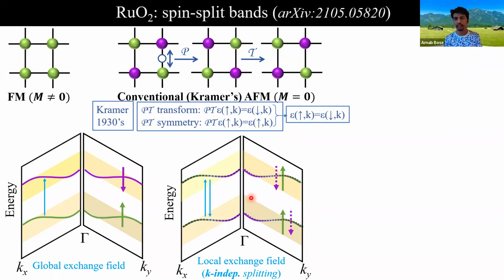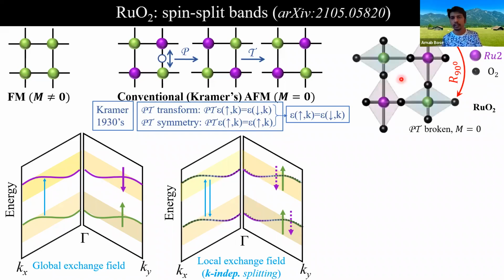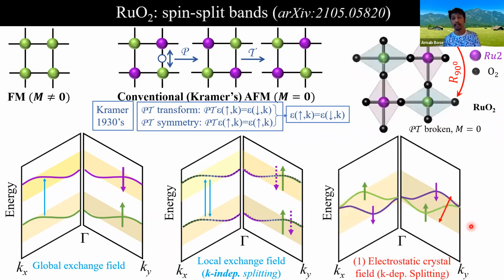Now let's have a look at what happens for the single crystal ruthenium dioxide that we are interested in. So this is the crystal structure of ruthenium dioxide. These are the non-magnetic oxygen atoms, and these are ruthenium atoms. So 2 sublattices, one is up spin, another is down spin, resulting in net magnetization of 0. Now, if we ignore these non-magnetic oxygen atoms, then it exactly looks like this standard collinear antiferromagnet. But the moment we consider the non-magnetic oxygen atoms, it immediately breaks PT symmetry. Rather, we have 90-degree rotational symmetry. So in this case, we cannot apply Kramers' theorem anymore. And recent theory works predict that it will exhibit spin split bands in the band structure that depend on k, unlike the regular collinear antiferromagnets, even though the net magnetization is 0.